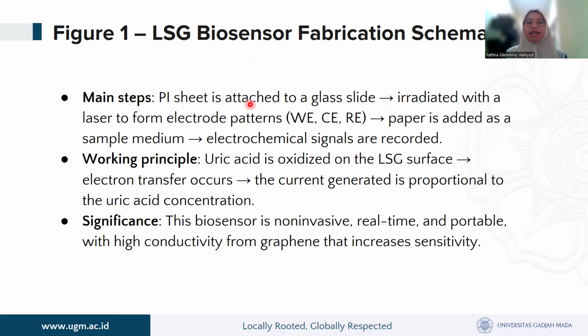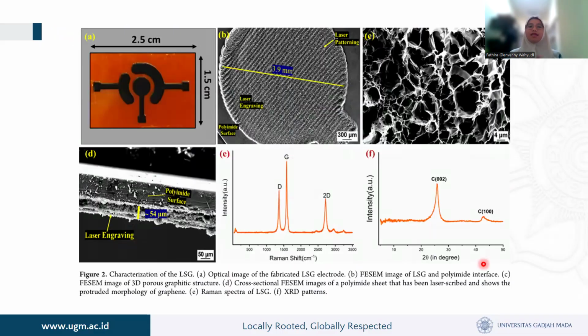The steps: the PI sheet, or polyimide sheet, is attached to a glass slide and irradiated with a laser to form electrode patterns. The working, counter, and reference electrodes are formed, paper is added as a sample medium, and then electrochemical signals are recorded. Working principle: uric acid is oxidized on the LSG surface, so electron transfer occurs. The current generated is proportional to the uric acid concentration. The significance: this paper-based sensor is non-invasive, real-time, and portable, with high conductivity from graphene that increases sensitivity. Let me move to feature 2.